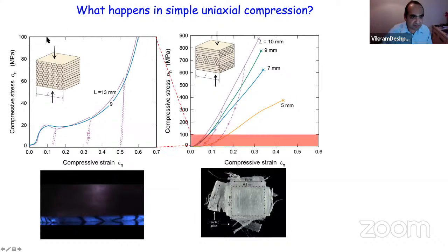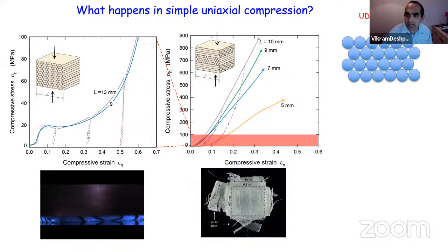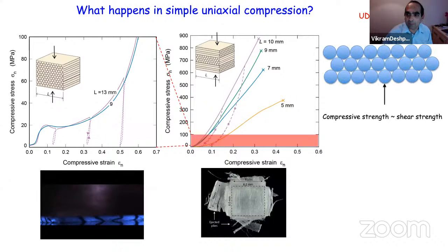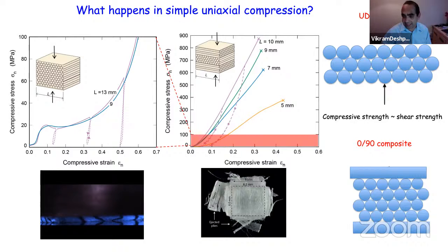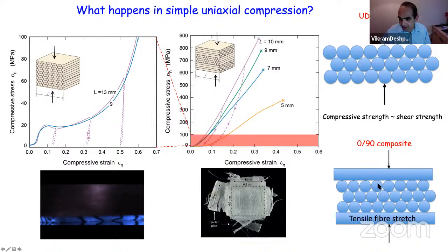And you get significantly higher strengths, right? This thing went up to 100 megapascals. This thing has failed at 900 megapascals. And the reason this is happening is that a UD composite will just compress like a bunch of logs. If you press it, it'll just shear over like that, and that's how the compression occurs. But now if you make it into a 0/90 composite, something completely different happens. As you compress it, these 90-degree fibers, because effectively they're bonded here, and the shear lag has developed some kind of shear strength here, you are now stretching those fibers in this way. And so now, to compress the composite, you need to push the 90-degree fibers into tension, which completely changes the deformation mode and hence the compressive strength.